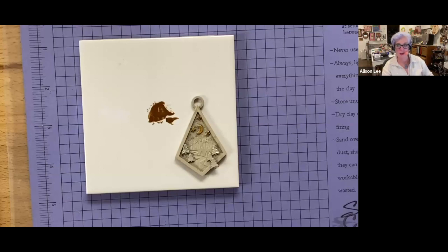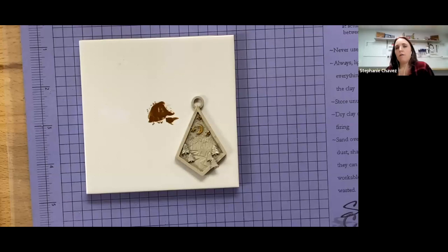And Ann wants to know, can you use this on fine silver, enriched 950, and sterling? Yes, I have tried it on all of them. When you are doing keum-boo, it is common practice to do what is called depletion gilding. What that does is bring the fine silver to the surface of the metal so the gold adheres better. However, I haven't found that I've needed to do that with the enriched silver blends of clay. So like your 950 or 960, I've just applied the gold straight to it and it's been fine. I still would, as a precaution for the sterling silver clay, depletion gild it.